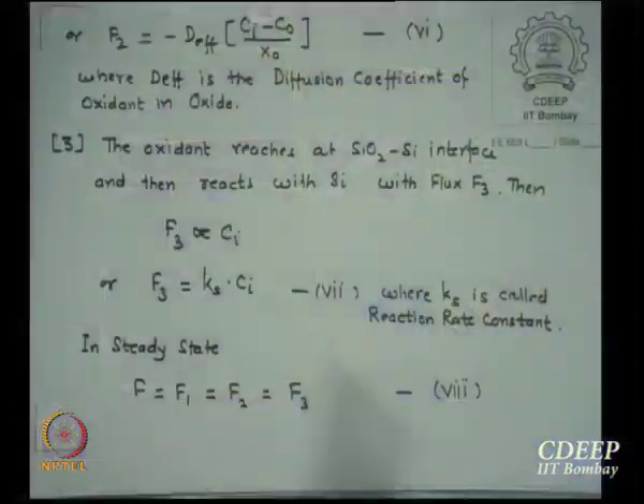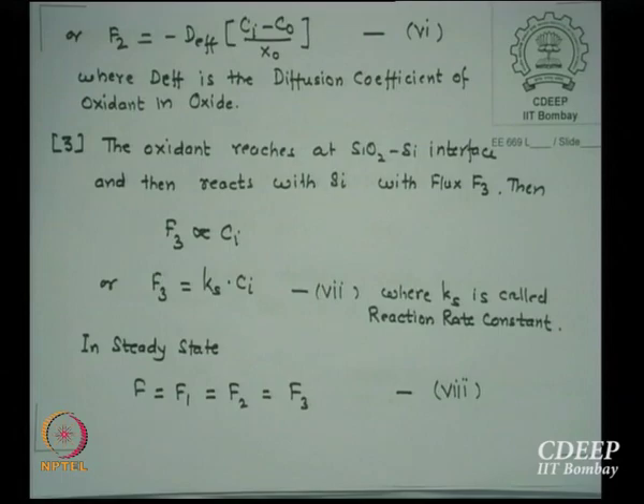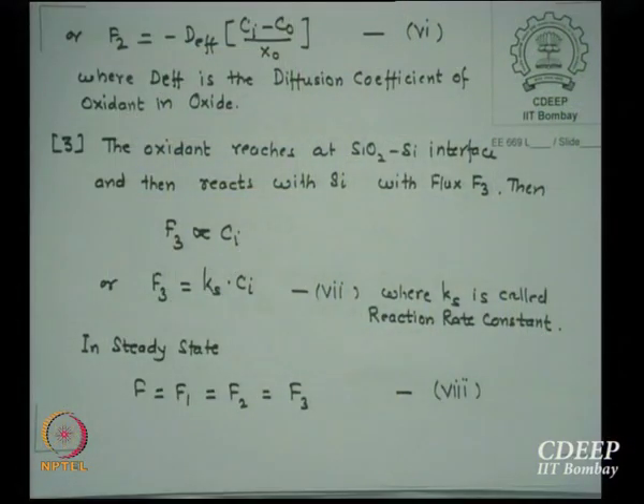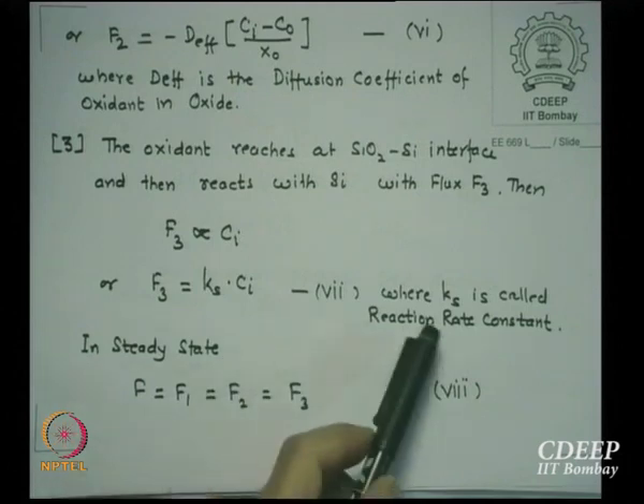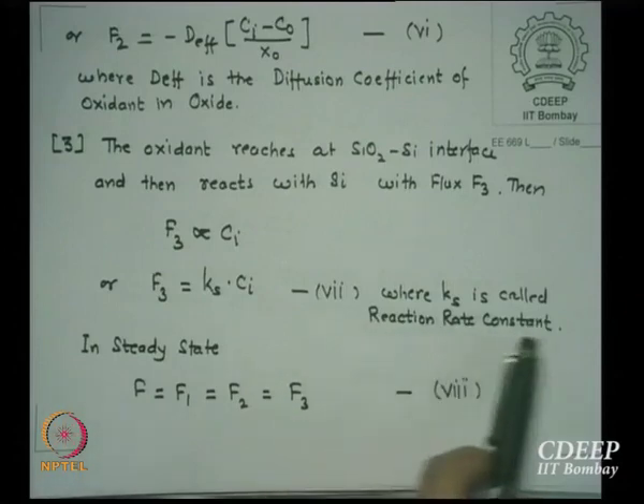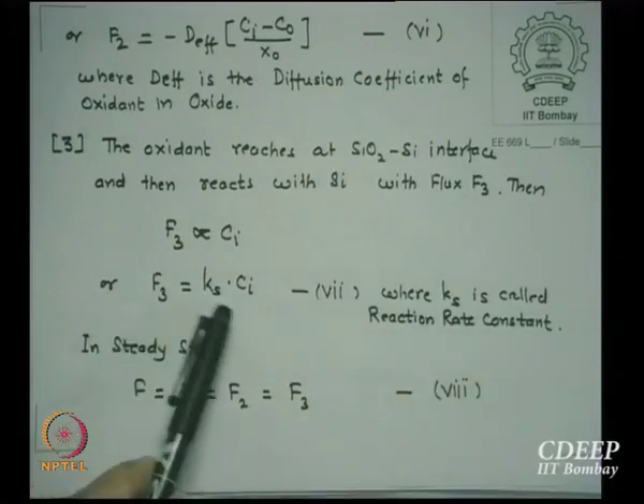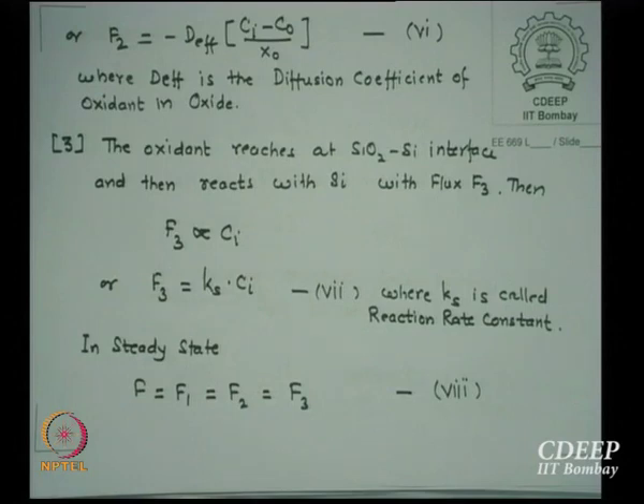So we want to know what is flux 3 which is proposed. Flux 3 is essentially as many silicon atoms are available, or concentration of silicon available, Ci at that place, that is the only one which it can react with. Oxygen cannot react more than Ci because whatever is available only can react. So we say the flux F3 is proportional to Ci, and the proportionality constant is called the reaction rate constant Ks. Ks is called reaction rate constant. So F3 is Ks times Ci. So now I have three fluxes.